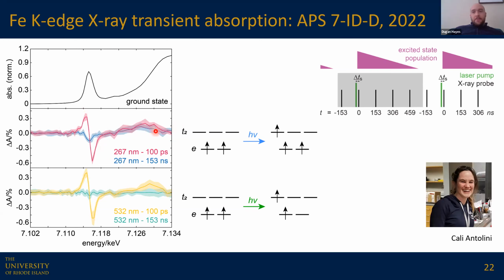And the thing that was initially puzzling to us when we did these measurements was that the spectrum that we saw following UV excitation is actually consistent with a transient iron 6 metal centered state, not the iron 5 that we expected to see following the ligand to metal charge transfer. And indeed, it looks very similar to what we see when we excite using visible light, exciting that metal centered state directly. But you can see there are some small differences. And by 150 nanoseconds following visible excitation, we see no signature at all in the difference, but we do see this dip following UV excitation.